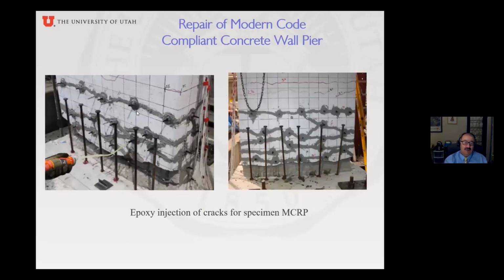Of course, we also use epoxy injection to close any cracks. But you can see we didn't do anything down here. We didn't patch the concrete or nothing, because that takes a lot of effort. Instead, we build the donut and then we fill it with grout. But the donut, of course, is very strong for confinement, has carbon fiber layers that are many, and so it protects all this area and will force the wall to actually fail above this area. We call this moving the plastic hinge up.